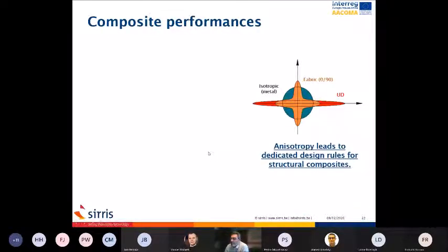Now, concerning composites, when we discussed a little bit earlier the performance of the fiber used for the composite compared to the metal or to the competitors, I mentioned the fact that we were talking about the performances of the fibers, not performances of the composite. Now we are going one step further with the performance of the composite, taking into account the parameter architecture. To understand it, you see that, for example, we take a carbon fiber with very high performance in one direction, the horizontal one. And we want to compare it with the isotropic material, the metal. And you see that, of course, the fiber proposes better performance, even 2 or 3 times or more than the metal, but only in one direction, while the metal proposes the same performance in all directions.